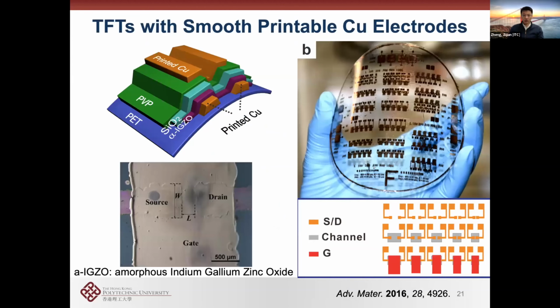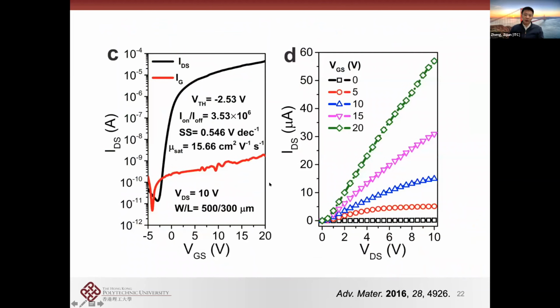Of course, we can push it further to do a transistor where we actually printed this copper as source and drain electrodes, and then we do all the semiconductors and insulators, and then print another top gate, right? So it looks like this, on a 4-inch wafer with different channel lengths. We show that with this low temperature printing and processing, the transistor looks actually pretty good. Good mobility, a good on-off ratio, very low threshold voltage, and a nice SS. A little bit of hysteresis because of the low temperature processing. In principle it's very difficult to get rid of the hysteresis in the semiconductor and the contact.